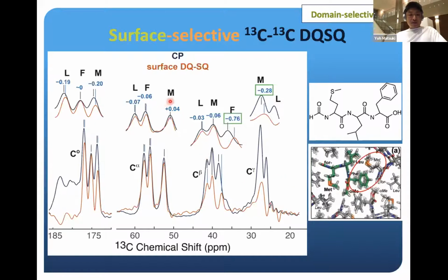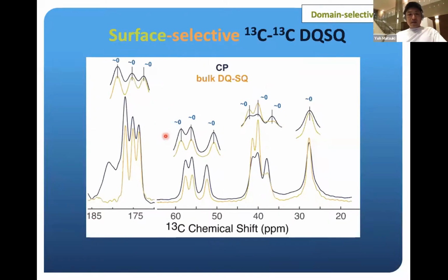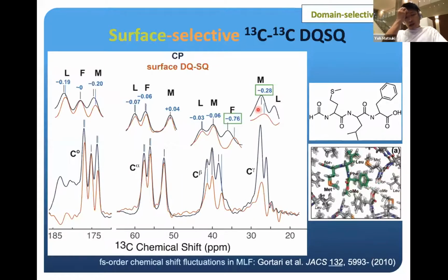The peak shifts are sometimes slightly positive, slightly negative, and almost no peak shift over here. So it's clearly site-specific. In the beginning, I was like, is this real? But if I look at the conventional DQSQ, again, this is the bulk DQSQ compared with the CP in black, almost no peak shift was observed at all, as it should be, right? So I conclude that this is real.